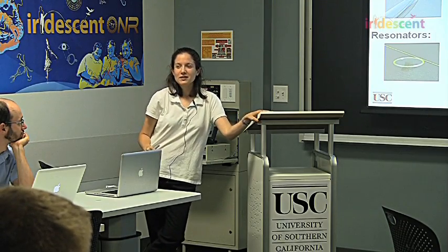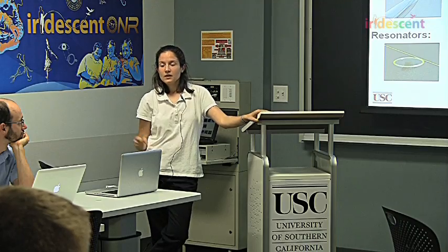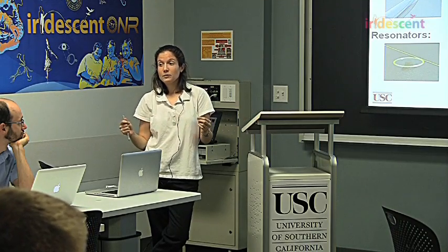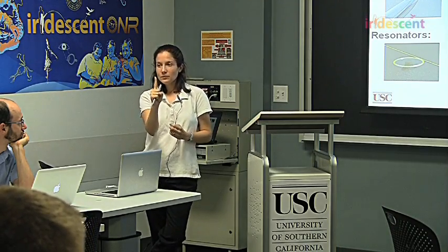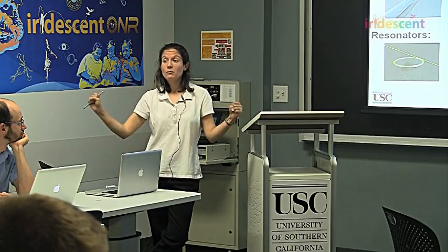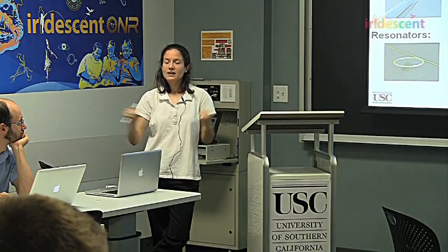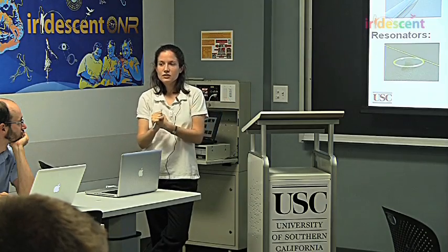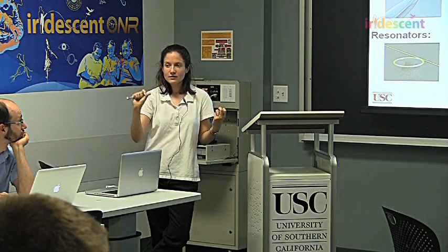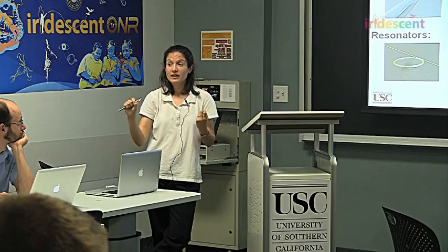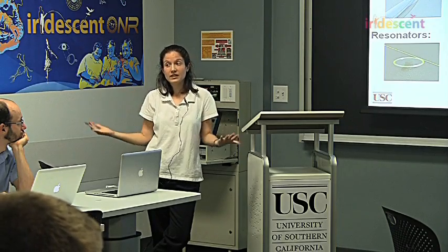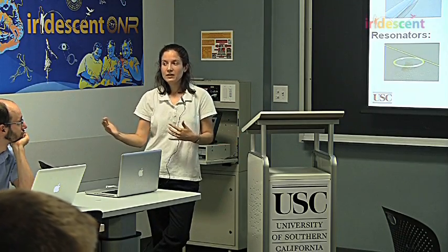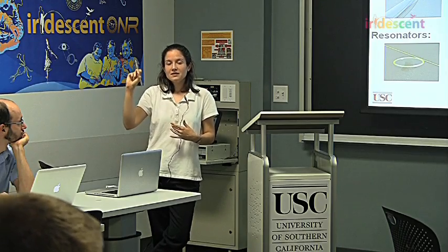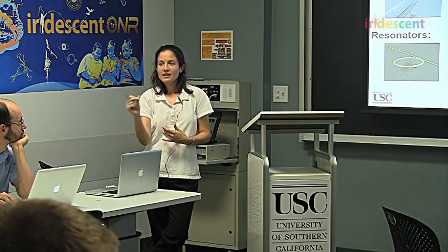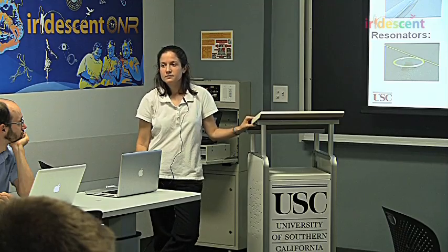You can also use something called a tapered optical fiber waveguide, which is where you take a piece of optical fiber, you heat it in the middle with a hydrogen torch, you pull on both ends, and then it melts, so it's kind of like pulling glass. And as long as you pull it until the diameter is smaller than the wavelength of light you're using, so if you're testing at 1550 nanometers or 1.5 microns, then the diameter has to be a micron or smaller, then you can also use that to couple light in.